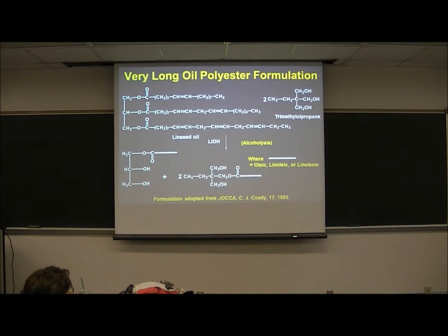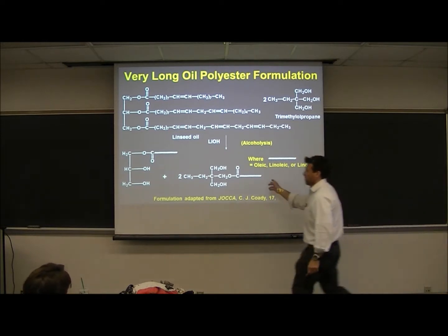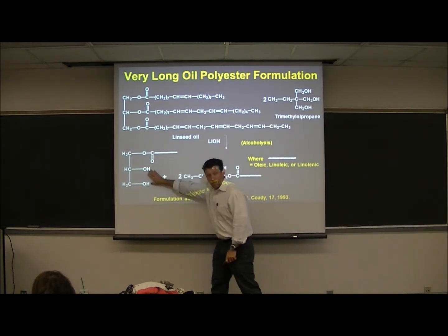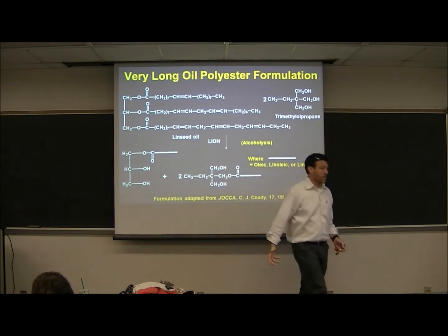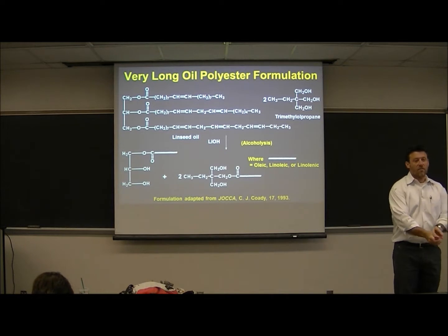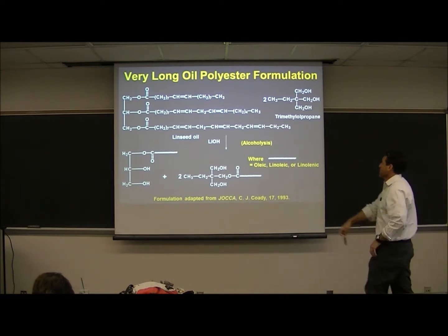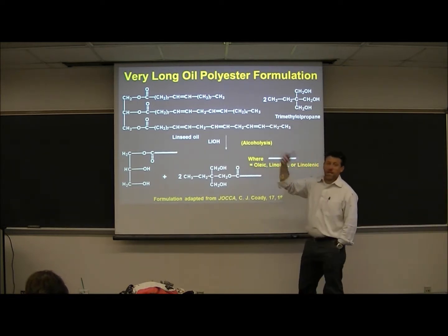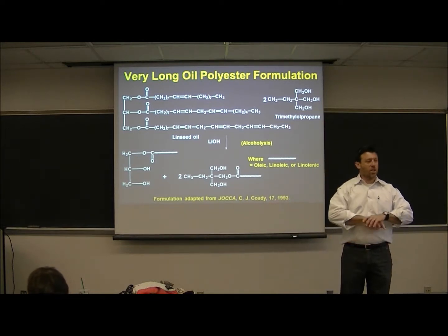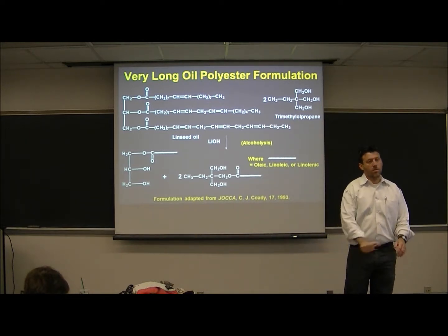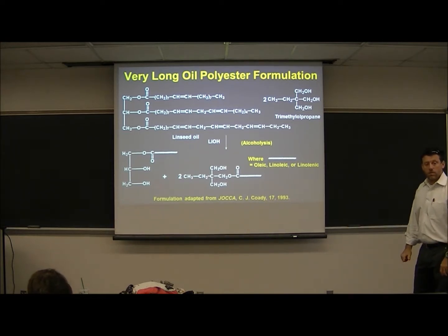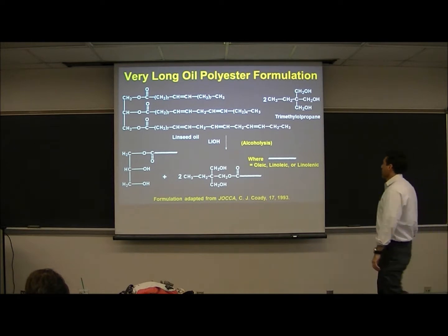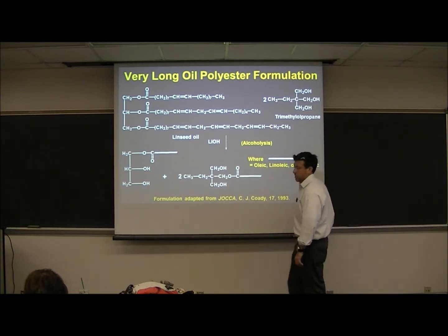It's easy enough to draw this. This is our goal. We have to make all of our monomers into AA monomers, and they're different types, but they're both AA monomers. We have to get to that to have usable material. In fact, if we just dump this in with the rest of what I'm going to show on the next page and try to run it all at once, we would get a gelled piece of junk that was useless. So we have to do this step first. How do we tell progress? Here to here.